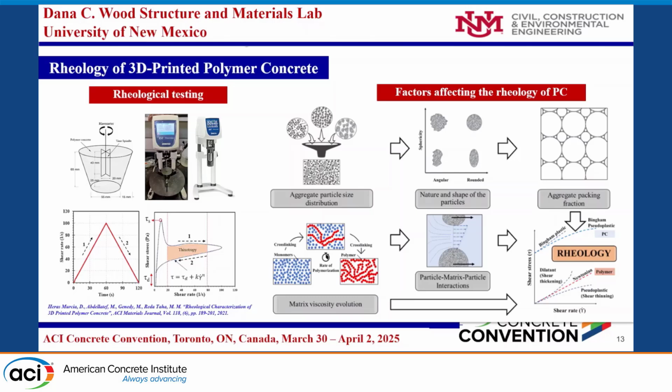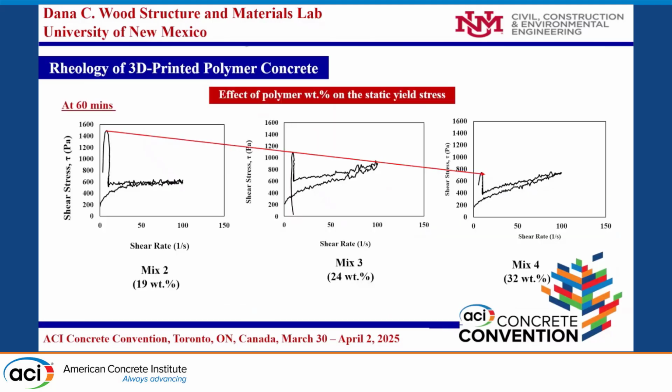shear stress, and they start having thixotropy, and the model is then a Bingham plastic model, and it can be modeled using the Herschel-Bulkley equation, where the maximum is the static yield stress with this hysteresis loop here, and the slope is the viscosity, and the y-intercept is the dynamic yield stress. The area between the two curves is the thixotropy.